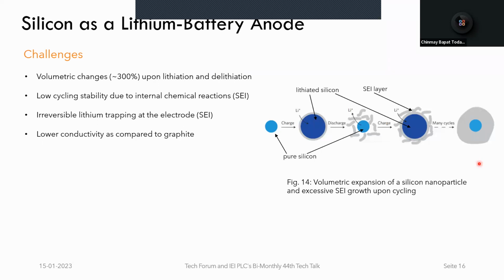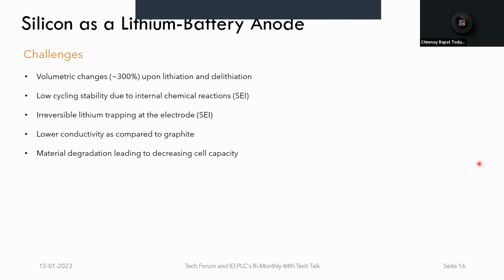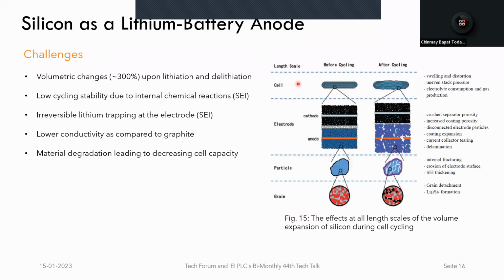Silicon, as I mentioned, has a lower conductivity individually as compared to graphite, and therefore we need to add conductive additives in the anode active material as well as in the electrolyte to improve the conductivity. Material degradation due to the silicon expansion and contraction leads to decreasing cell capacity from granular to cellular level in various phenomena such as grain detachment, internal fracturing of the silicon particles, coating expansion and delamination of the anode active material from the current collector itself, swelling and distortion at the cell level, and also rapid electrolyte consumption and gas production due to the continuous SEI breaking up and reformation. As we increase the silicon content in the anode, the capacity degradation also accelerates.